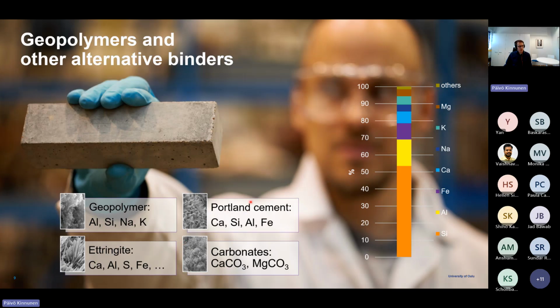So then another question that one has to ask is, okay, if we are going to take this powdery material and make it into some kind of construction material, you have to have some kind of binder that you bind those together. And so we have been working with Portland cement, but also different kinds of alternative cements, geopolymers, ettringite-based binders, but also carbonate-based binders. This is actually missing the hydrated magnesium carbonates that you can also use. So those are the different sort of minerals that you could, in theory, turn into binders. And let's look a little bit later more into that. It's actually missing a lot of magnesium-based binders, such as magnesium silicate hydrate, that we'll return to.